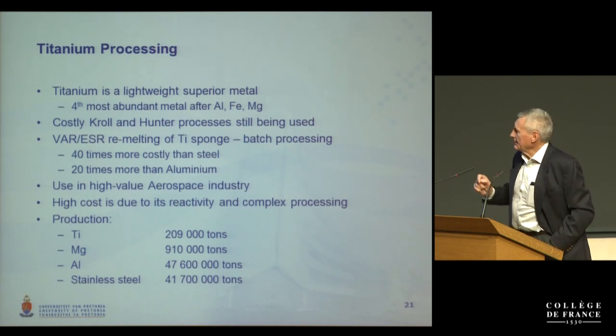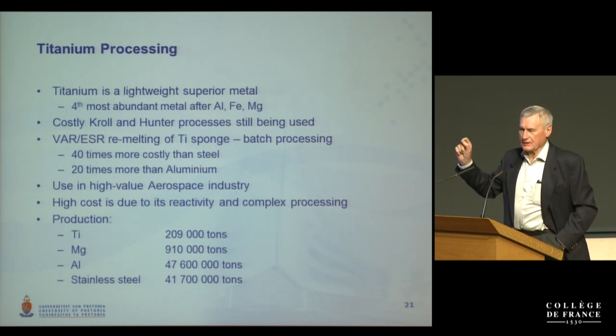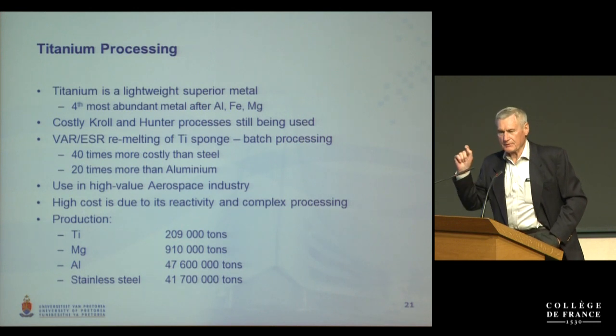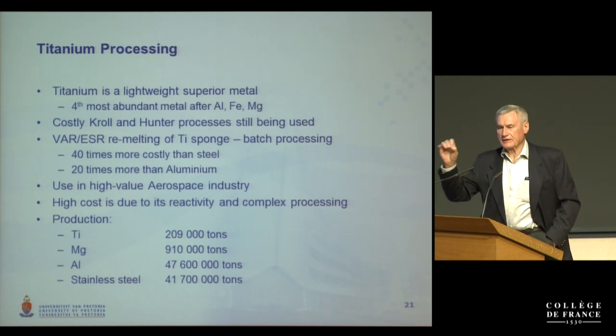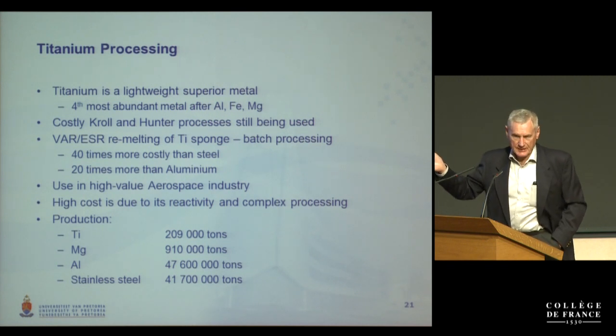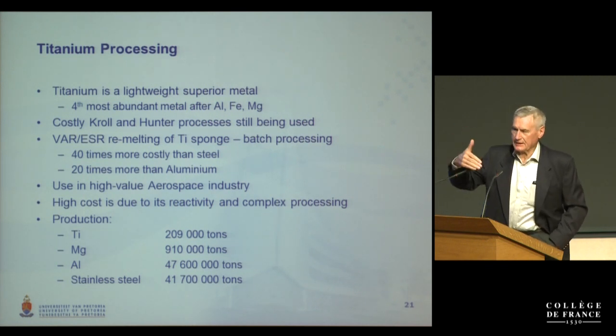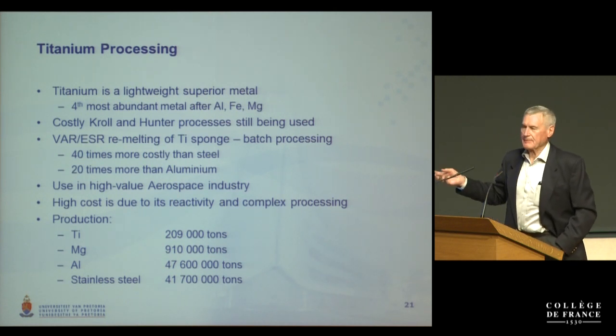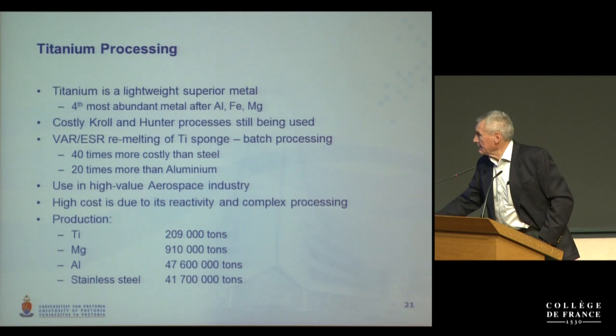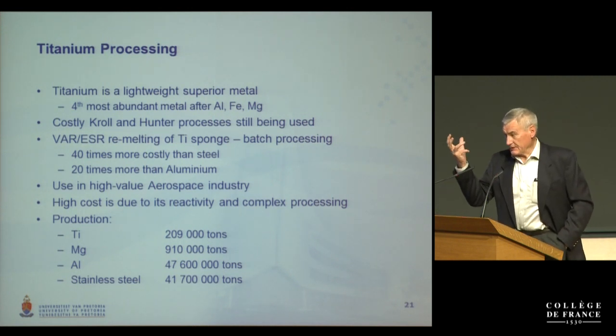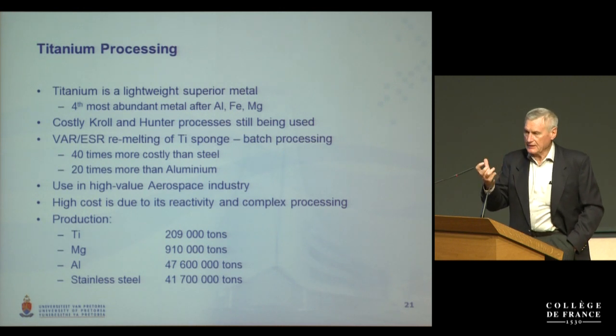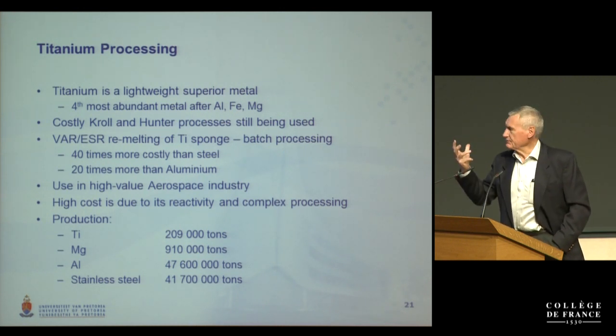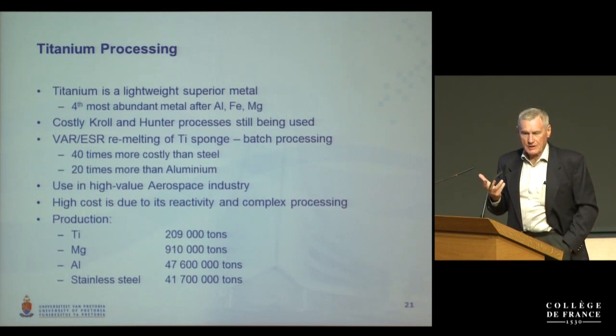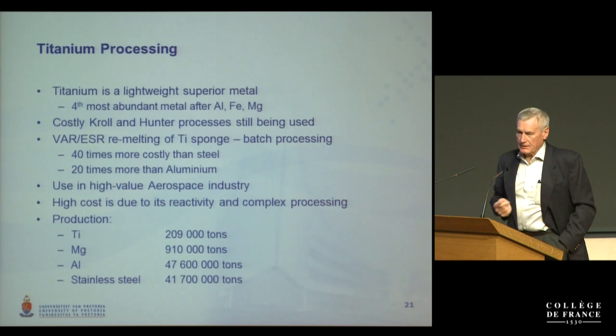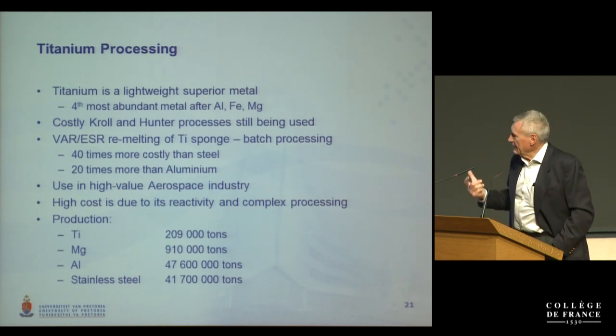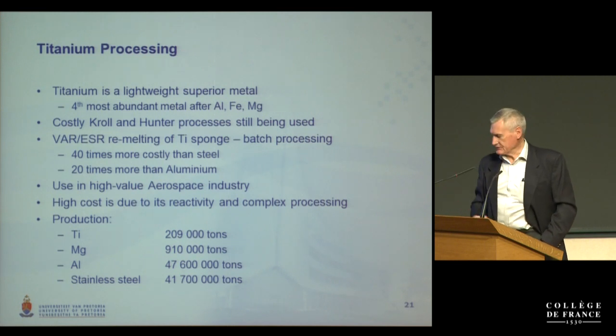superior metal. But the problem is that we're still using the so-called Kroll process, where we produce titanium tetrachloride and reduce that by magnesium, forming titanium metal plus magnesium chloride. Then you have to separate the magnesium chloride from this spongy titanium metal, and then it has to be remelted in a vacuum arc furnace or an electroslag furnace. So it's a major, complex, costly process to produce this.